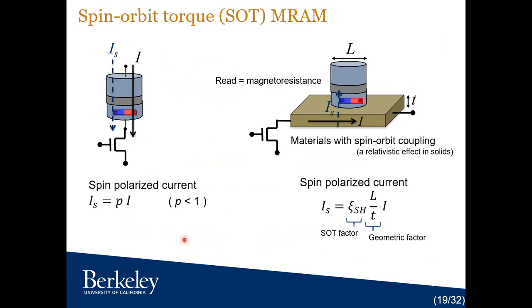So let me first talk about a different type of MRAM. That utilizes materials with spin orbit coupling. Spin orbit coupling is a relativistic effect in solids. What happens if you run a current through this material, you have a spin polarized current in the transverse direction. And this is different from the STT, because there you run a current in this direction, your spin polarized current is also in the same direction. It was polarized by the top magnet.